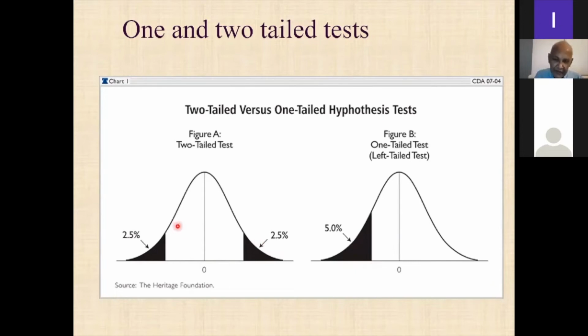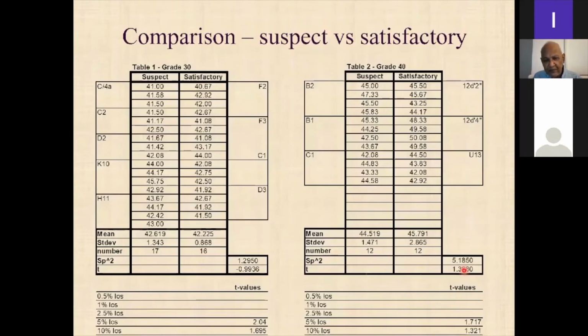In that first example, the suspect mean was actually greater than the satisfactory mean. So strictly speaking, we should do a test also to see whether they belong to the same population. If you want that test carried out at a 5% level of significance, you have a t value here and a t value there, and it should lie in between. What we actually get is just a single t value, so it doesn't matter whether it comes out minus or plus. But you use a two-tailed test for this sort of thing and a one-tailed test for this kind of thing. You find that the t value for a 5% level of significance is 2.04.